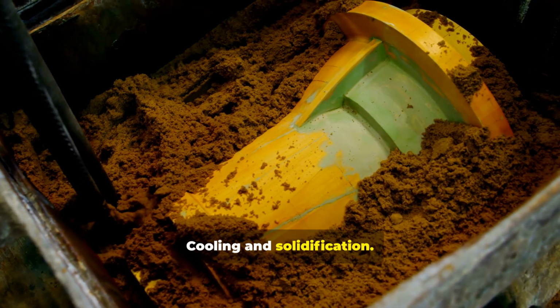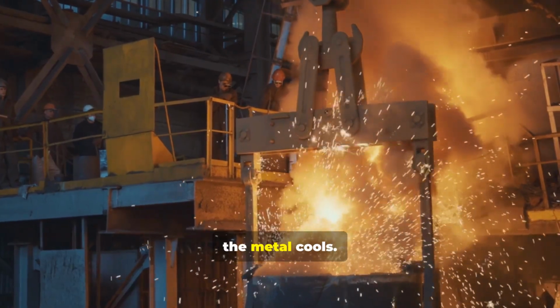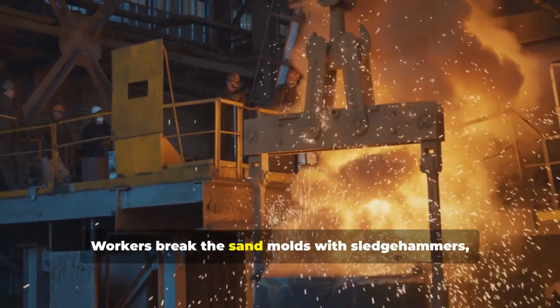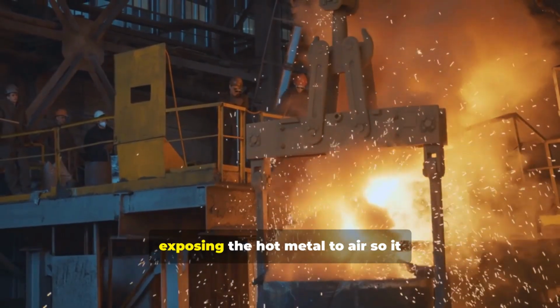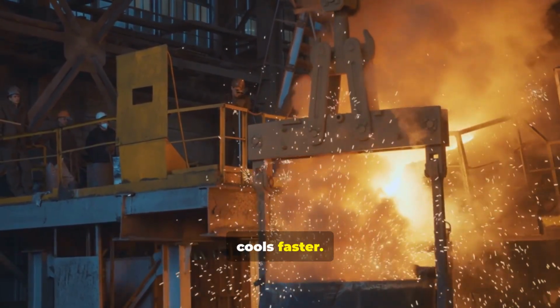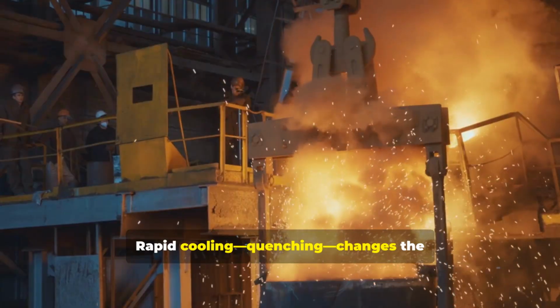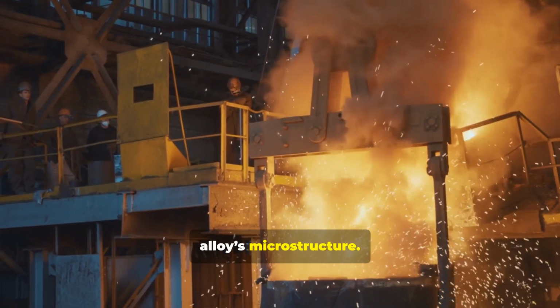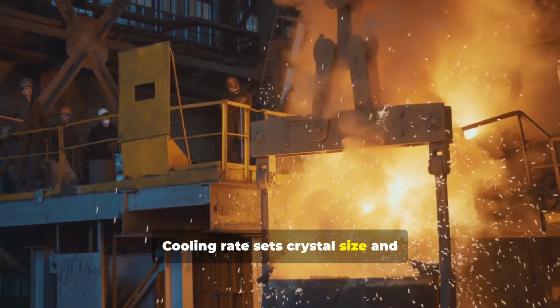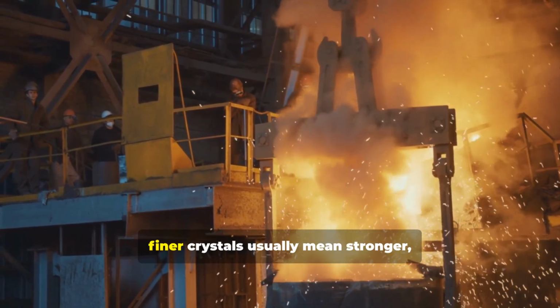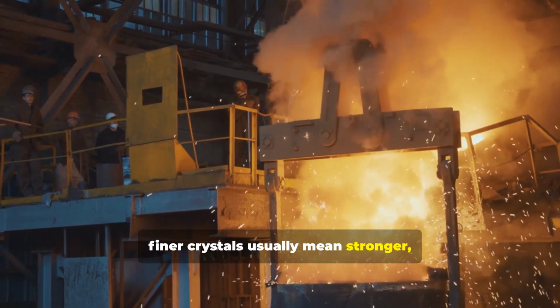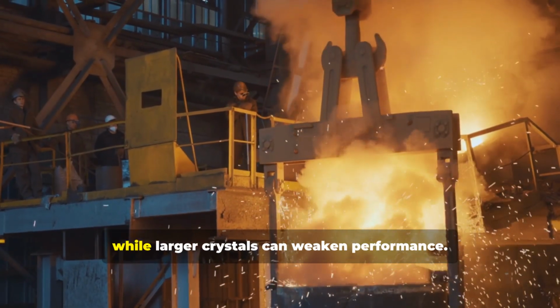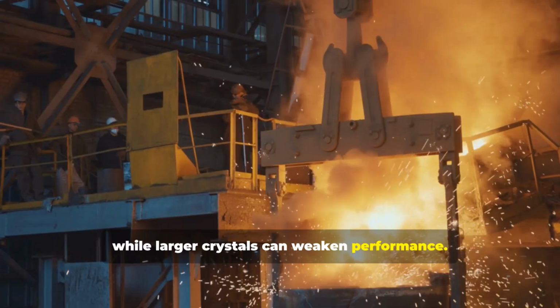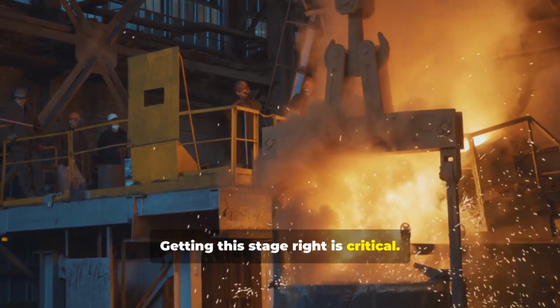Cooling and solidification. Once the molds are filled, the metal cools. Workers break the sand molds with sledgehammers, exposing the hot metal to air so it cools faster. Rapid cooling, quenching, changes the alloy's microstructure. Cooling rate sets crystal size and arrangement. Tighter, finer crystals usually mean stronger, more reliable magnetic properties, while larger crystals can weaken performance. Getting this stage right is critical.